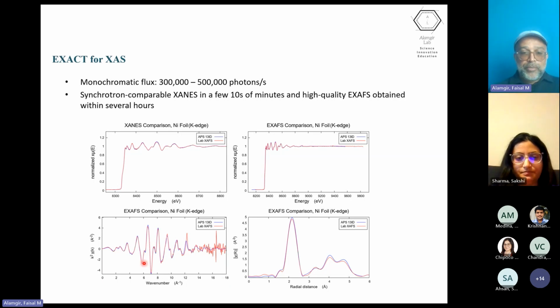So the point of this is that there's no embedded artifact coming from the lab-based instrument. They're giving you very similar information to the beamline, and a simple rule of thumb would be that in concentrated sample cases, it takes about 6 to 7 times more time to get similar quality to what you'd get at a bending magnet beamline.